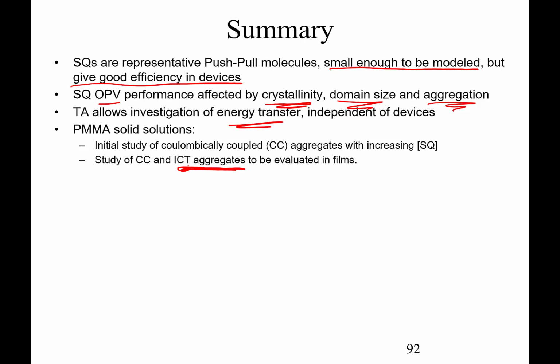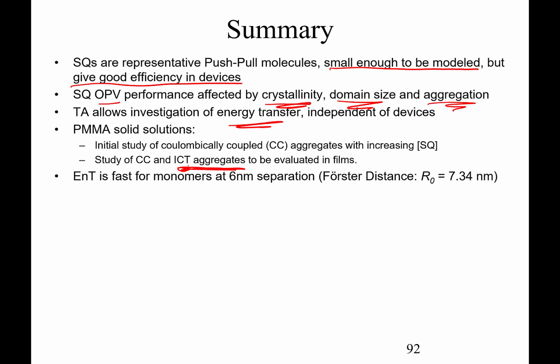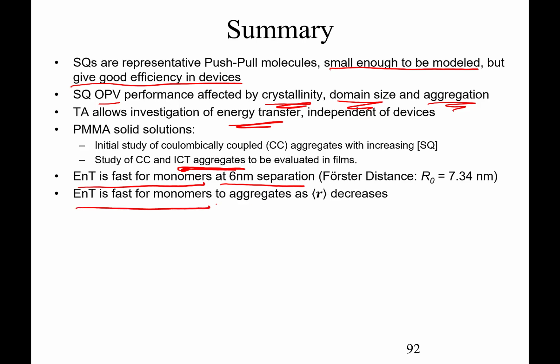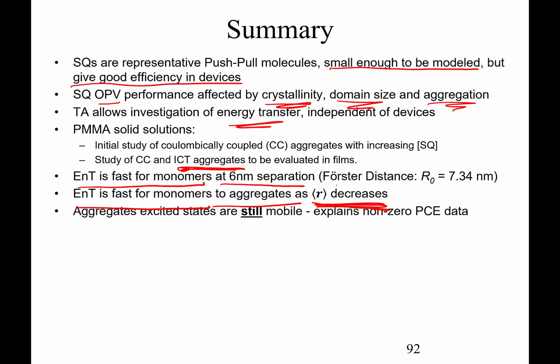It turns out that energy transfer is fast for monomers at 6 nanometers separation, and we can calculate that from the concentration of the Squaraine in the polymethyl methacrylate. So energy transfer is fast for monomers to aggregates, certainly as the average intermolecular separation decreases. The aggregates' excited states are still mobile, and that's why we don't get a zero power conversion efficiency for our devices. They still work.